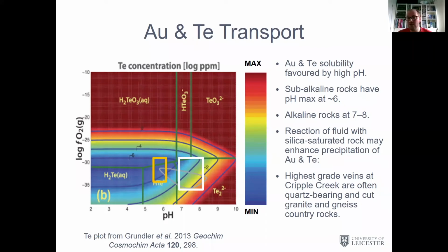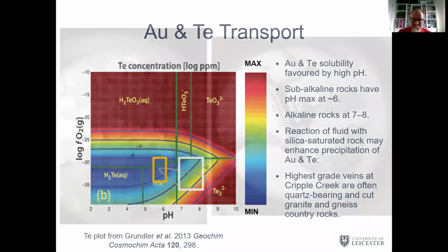Tellurium is one of the very few elements on the periodic table that will actually form stable minerals with gold, and it forms a lot of different stable minerals with gold, different polymorphs and different combinations with silver, lots of different sulfur salts. So although it can produce high-grade gold, and it usually mirrors that gold grade with tellurium grade, it causes us some exploration problems in terms of those quartz targets, but also some processing problems in terms of the tellurium causing problems for gold extraction.